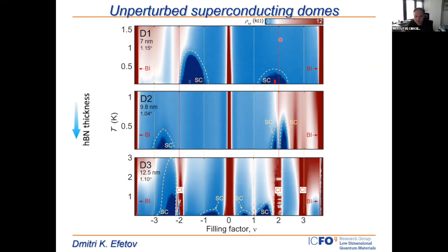In what we measure in transport, we can only measure temperature activation of some sort of energy gap. So this is always underestimating the gap which is performed. Really, in my experiments here, we could only extract the gap in an unscreened device, and we can try to extract the gap through temperature activation in a screened device. But this is rather rough.